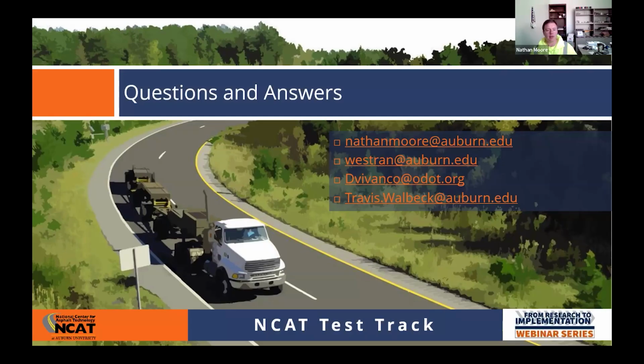Another question from Kevin Vaughn. Kevin says the NCAT study showed that a CT index of 15 was a good limit for identifying good field cracking. Many DOTs are setting much higher limits in the range of 70 to 100. Is this difference due to differences in aging methods, or are we setting limits too high? Yeah, it's a great question. And obviously, the mix results that I showed you there were critically aged mixes, not the plant-produced mixes or lab-produced mixes. So the numbers that you're hearing from some of the states, like 75, 100, even 125 in some states, those are not on aged mixes. So you've got to be very careful about reading the results. You need to read those details in the reports before you try to set criteria.